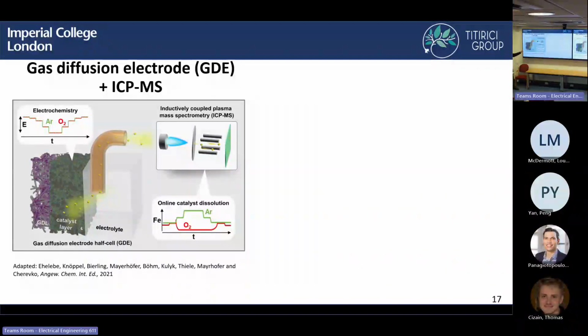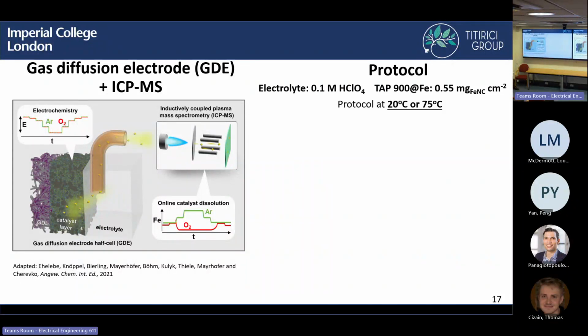So this is a setup that has been developed by Sergei Cherevko's group in Germany. And so again, we took a similar protocol of using 0.1 molar perchloric acid with our TAP 900 material. And we do the measurement at 75 degrees in addition to at room temperature.